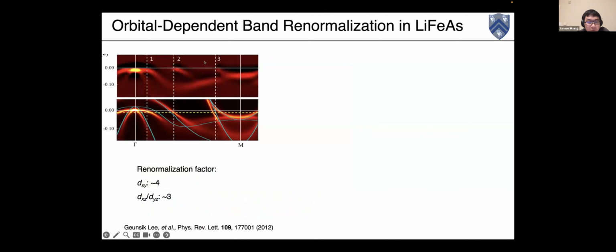And the previous experiments, ARPES experiments combined with DFT and DMFT, have revealed that there's an orbital-dependent band renormalization, in which the dxy orbital has a renormalization factor around 4, and the dxz/dyz orbital has a renormalization factor around 3.